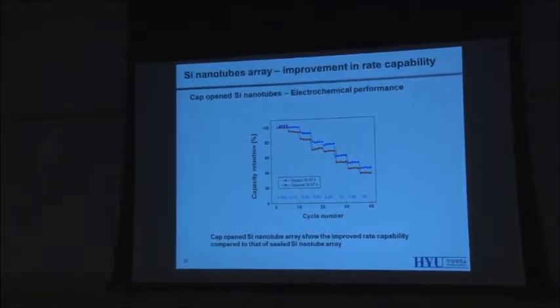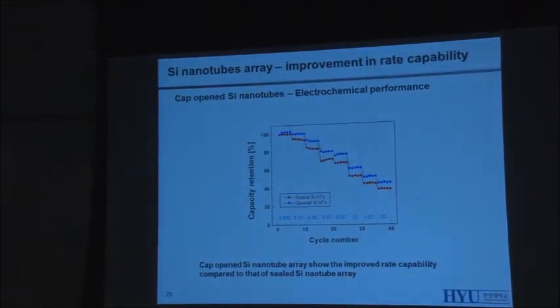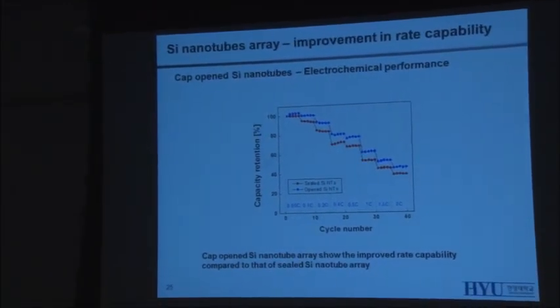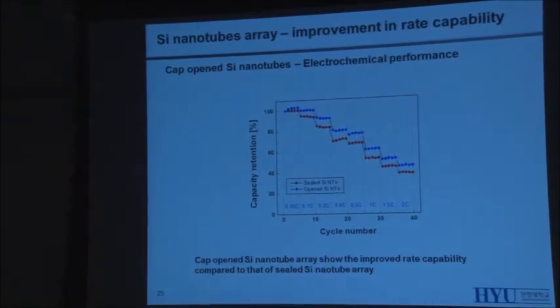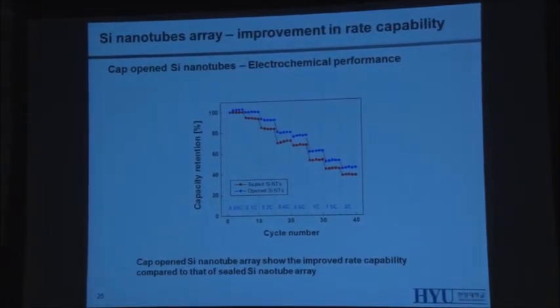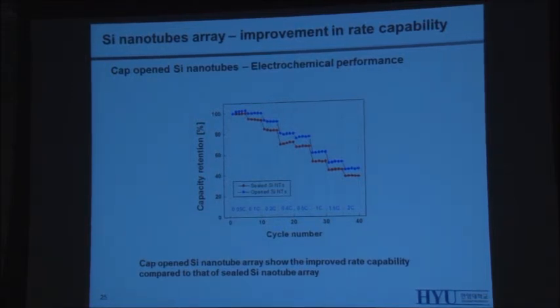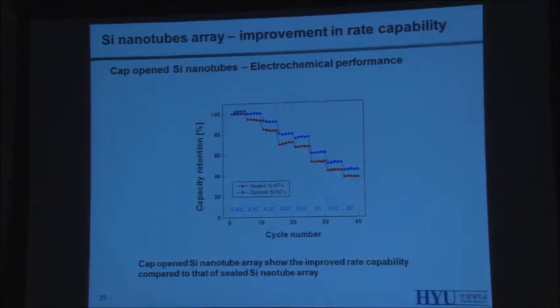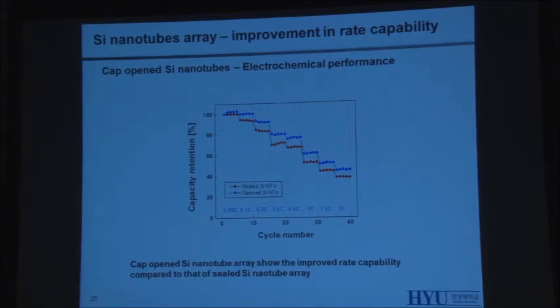So it's very weird, as you point out, that it should increase much better than this. But maybe the electrolyte could not penetrate the inside of the silicon nanotube. The diameter here is about 60 nanometers, so maybe the electrolyte cannot get through that capillary channel. How long are the tubes again? Three point seven microns? It's five microns. Five microns, yeah.